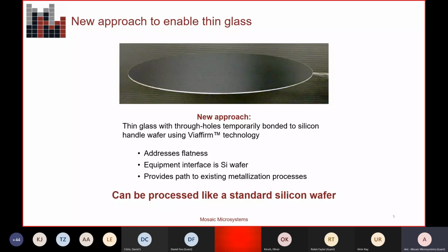So you basically put the wafers in contact, and it sort of self-propagates to establish that temporary bond. One way to think about this is it's kind of like a van der Waals bond, but if you have a van der Waals bond and put it in the oven at 250 to 300 degrees C, it becomes a permanent bond. You'll never remove it. With this approach, you can go up to 450 degrees Celsius, and it doesn't outgas, and it still remains temporary. So it really gives a very attractive way to process the thin glass like it's a silicon wafer, and allows you to leverage the existing supply chain to process thin glass.